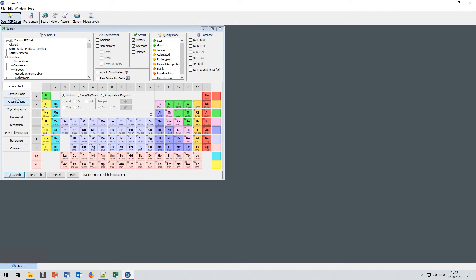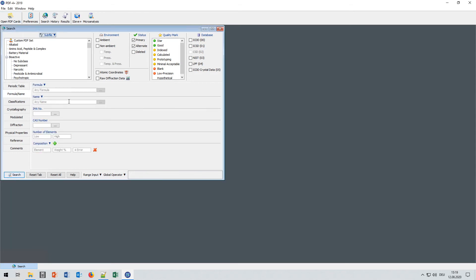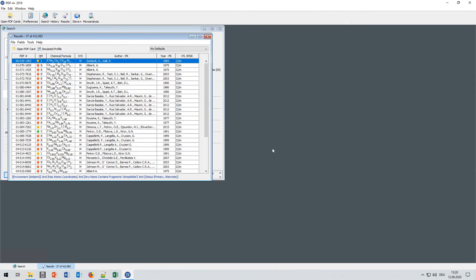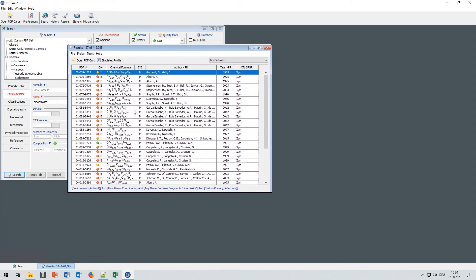So now we can search for this file. Maybe first search for the mineral Clinoptilolite. And we are only interested in datasets measured at ambient conditions. So let's check this. And for Rietveld refinement, we need atomic coordinates. We can only use structure files with atomic coordinates. So let's check this and ignore all other files without coordinates. Let's start the search.